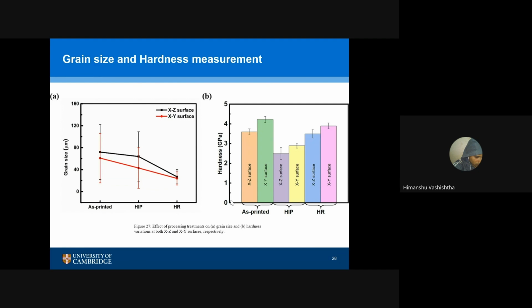Now, what this hot rolling or hot isostatic pressing is doing is applying pressure on the material. So you can see the grain size is coming down, and in case of hot rolling it's coming down significantly, right? It's somewhere close to 50% reduction in the grain size.